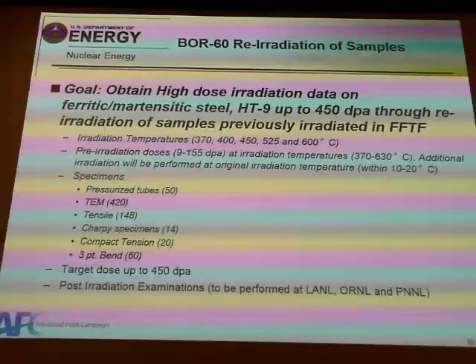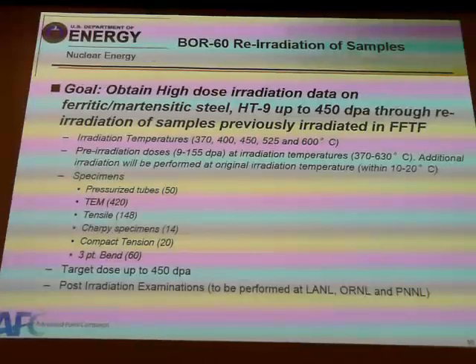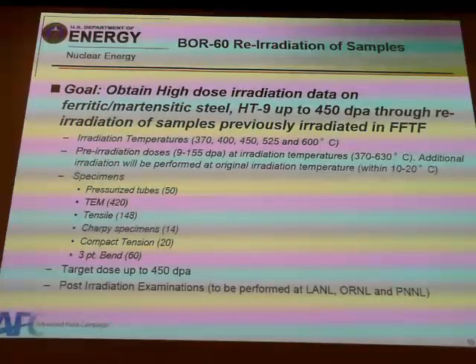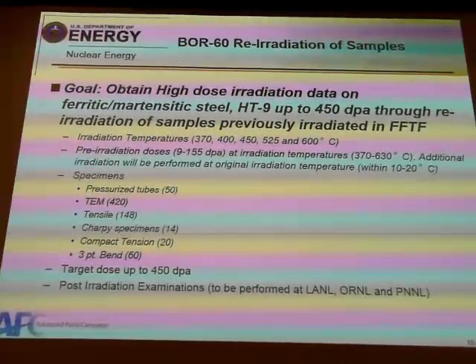So one of the ways we're doing this, though, to try and get data in reactor is we've taken some materials. This is previously irradiated materials at temperatures from 370 up to 600 degrees C, and pre-irradiation doses out to 155 dpa. And we put pressurized tubes, tensile specimens, TEM specimens, Charpy specimens back in the reactor.